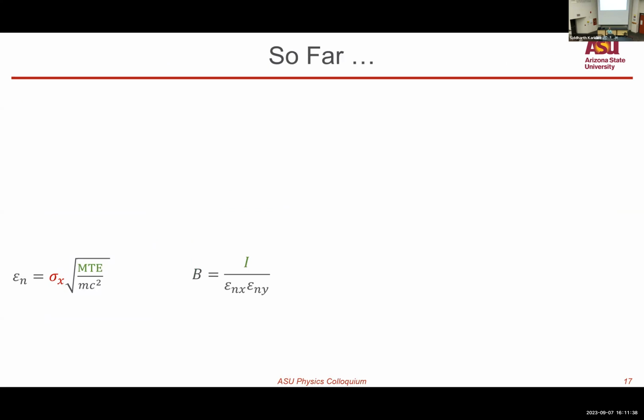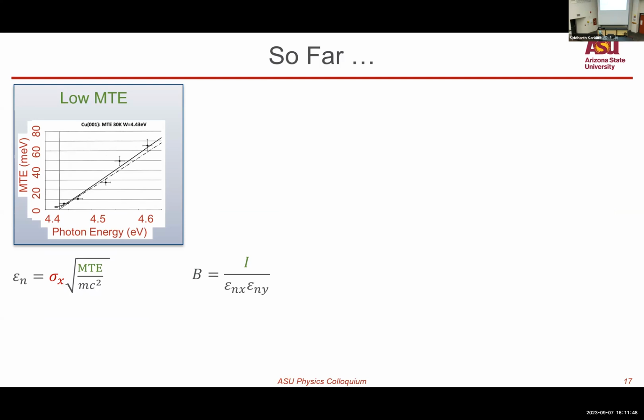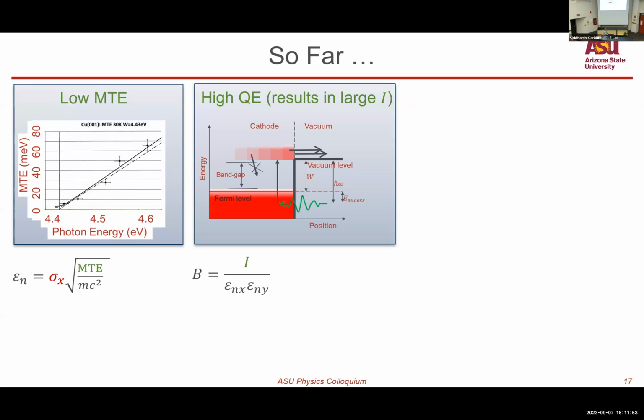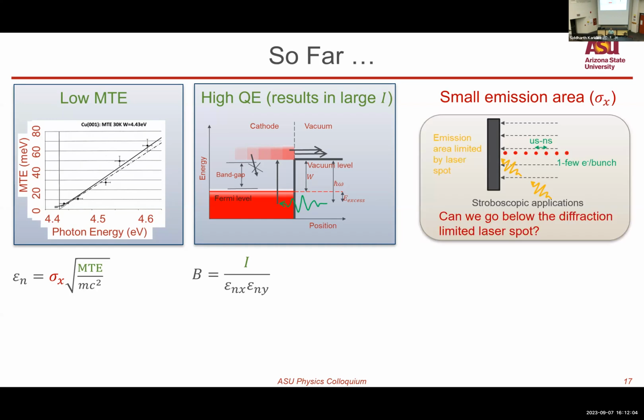Okay. So far, we saw what brightness is and how it's related to the current and the emittance, the spot size, and the MTE. We saw how we were able to obtain a very small mean transverse energy. We saw how we can maximize the current without exciting nonlinear photoemission using these high quantum efficiency cathodes. But what about spot size? So far, we haven't really looked at it. For small emission areas, we saw that for these stroboscopic applications with few electrons per bunch, the spot size is limited by the diffraction limit of light.